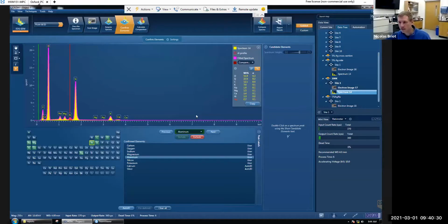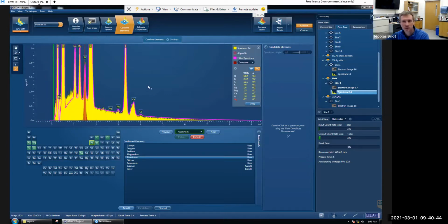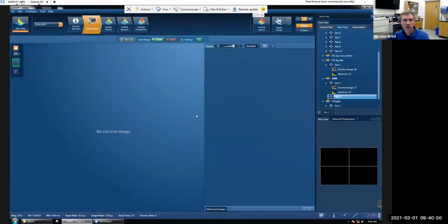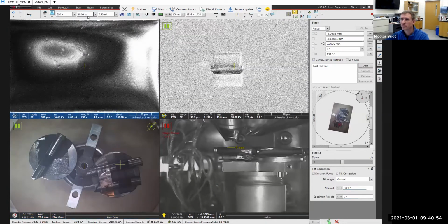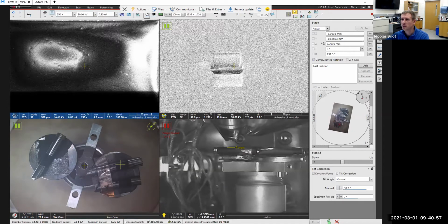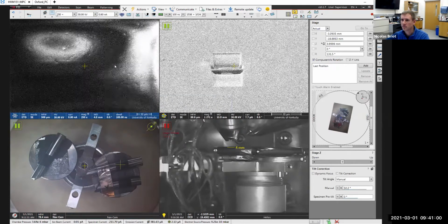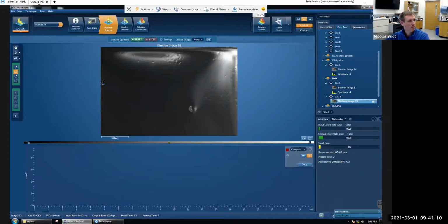Actually, let's try something. Let me share the EDS screen again and go to that potassium sample, right? This one. So in that 100K, we saw a little bit of silver, and XPS confirmed that. That was an analysis at 10 kilovolts in the EDS. I want to see if we see it if I bump up the voltage here. Let's see. I go much higher. What do we see? All right, grab the image, make a box, and see what's in there.